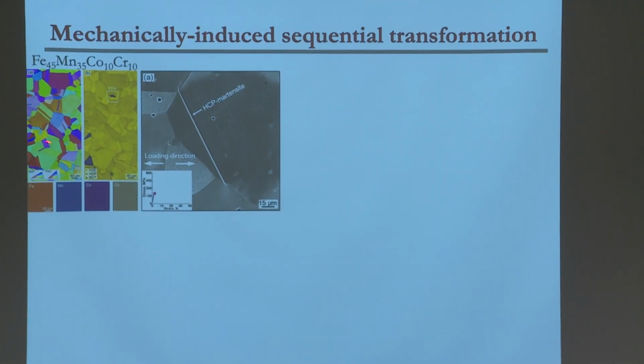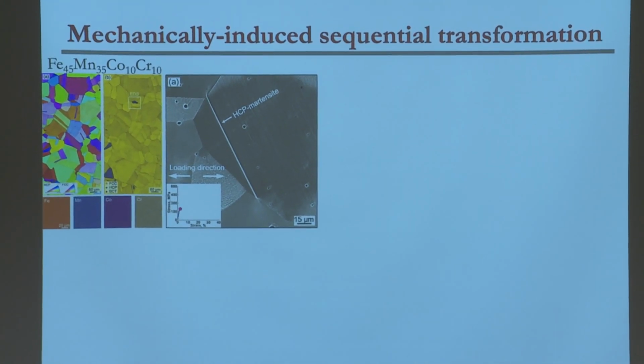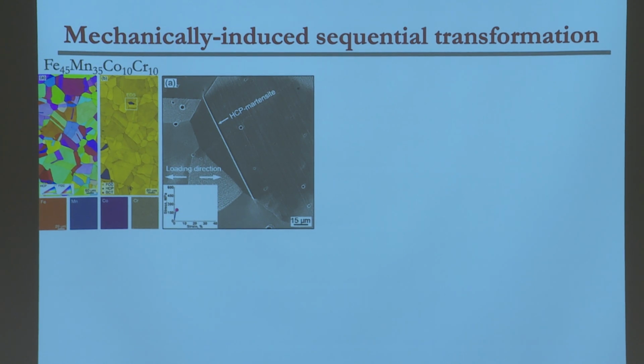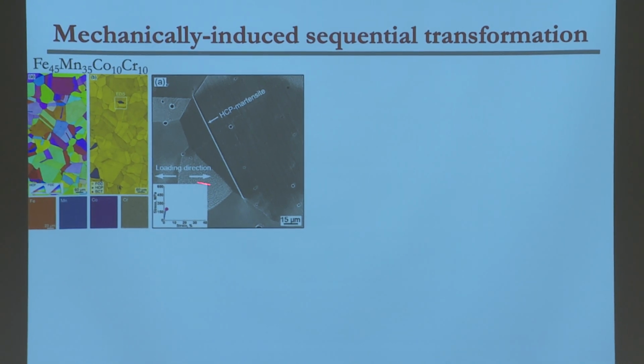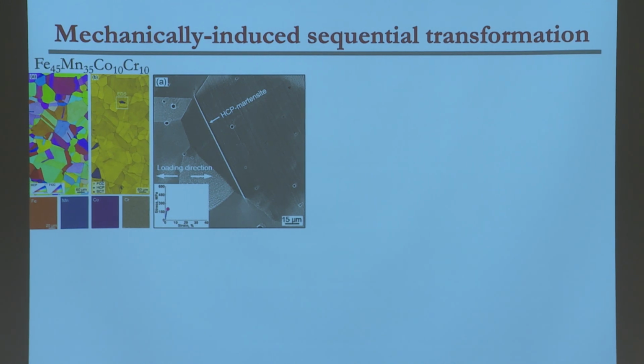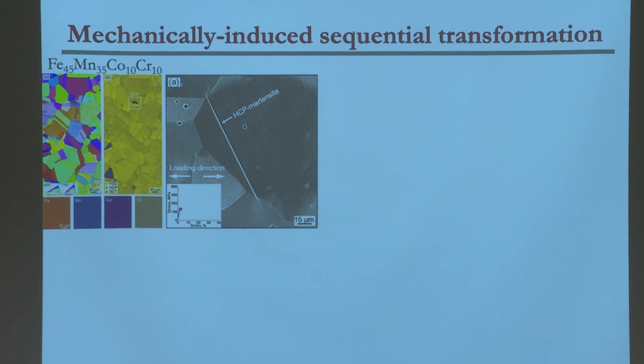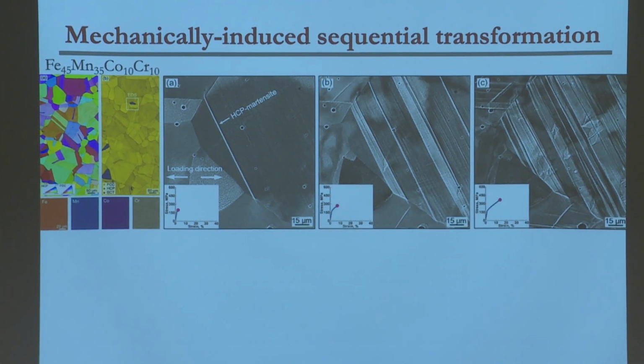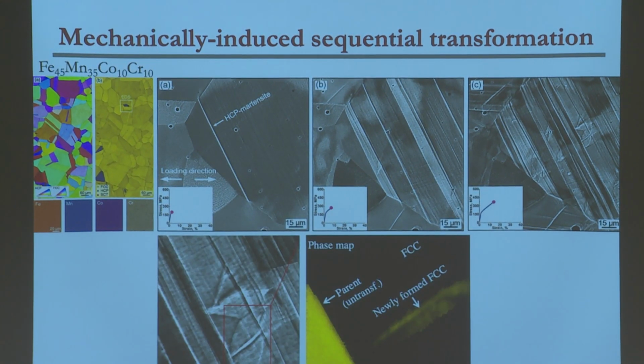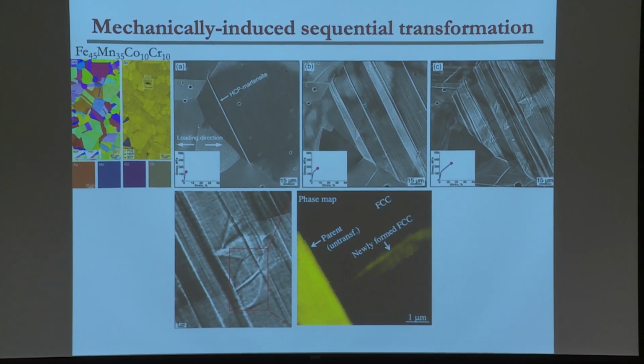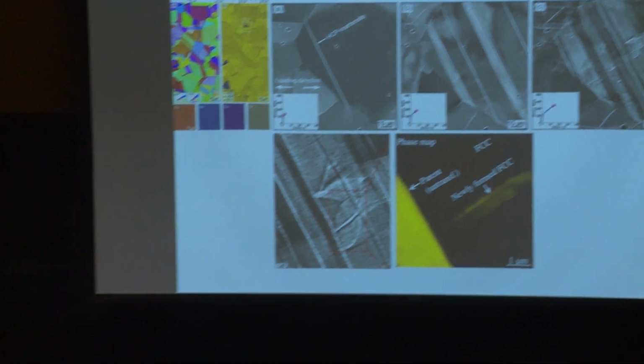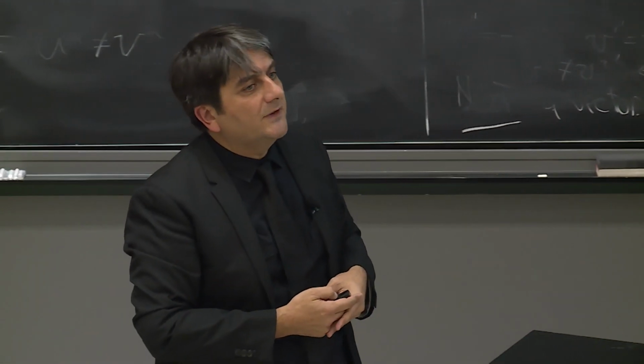And Shaldo has demonstrated this by carrying out in situ experiments again. Keep in mind, these, again, are very complex microstructures, very fine details, so we have to look at things as they happen. And here, again, these in situ techniques become very important. And what is demonstrated here for this particular alloy, iron, manganese, cobalt, chromium system, is that as you deform this FCC system, you will first have the HCP martensite form. And as you further deform, you see some surface features appearing. And by further analysis, diffraction analysis, EBSD basically, you can identify that this is a newly formed FCC phase. So you have FCC to HCP transformation, and then further deformation leads to HCP to FCC transformation. But keep in mind, we are very deep into the plastic regime here. So we are not looking into elasticity. This is not superelastic effect. We are talking about a newly formed FCC here.